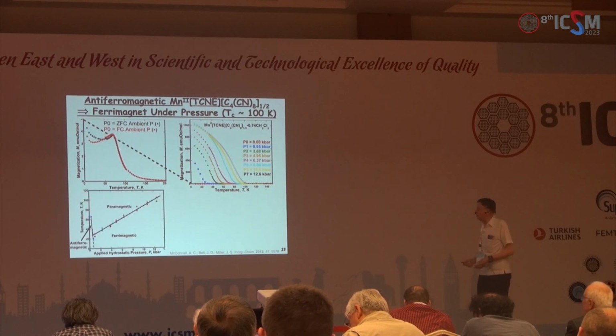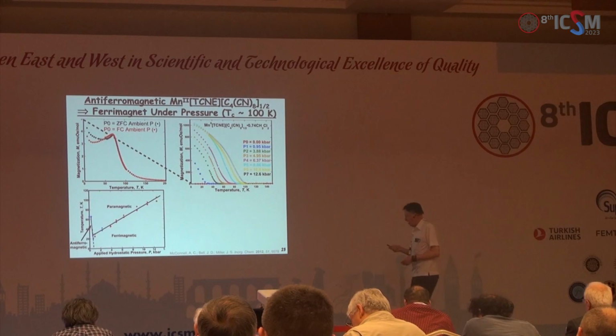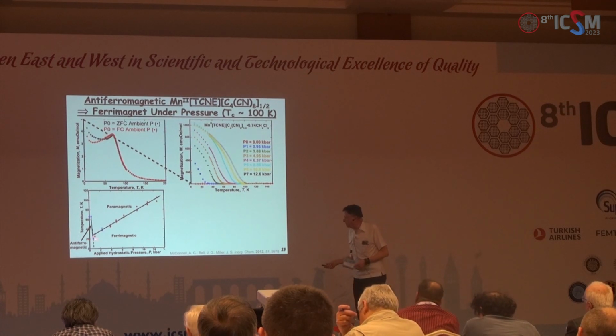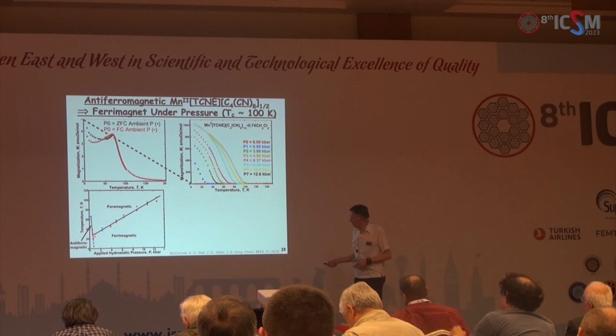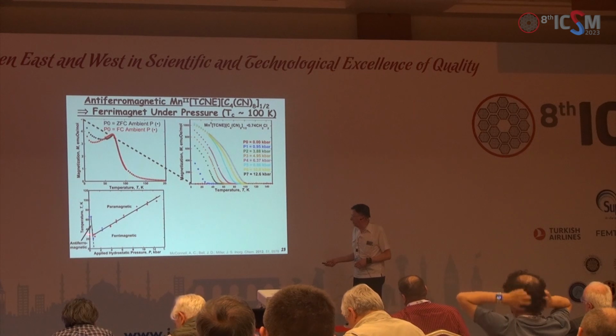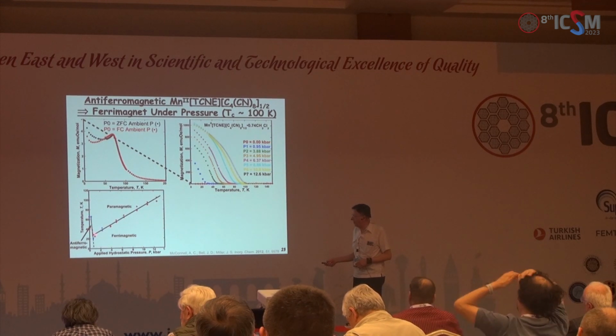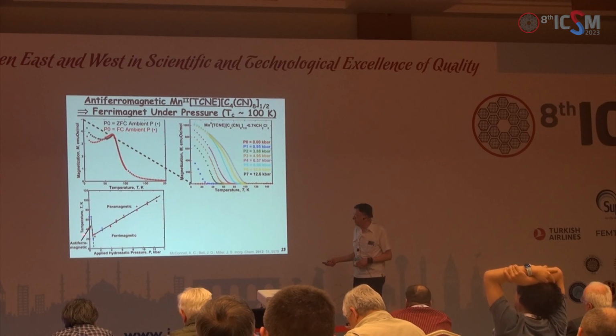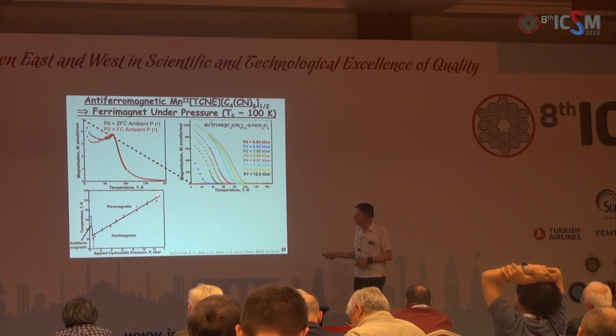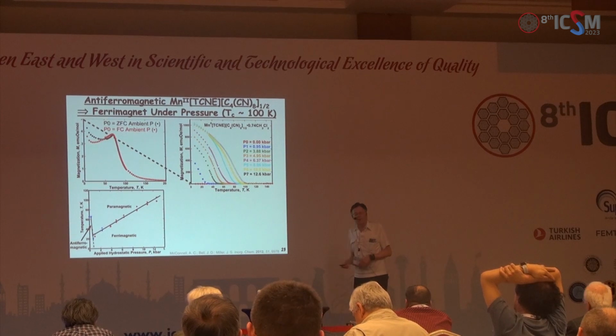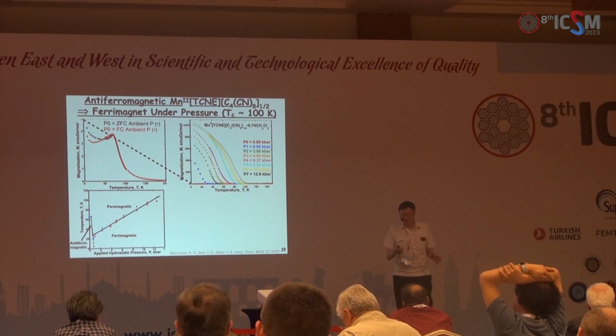If we look at the phase diagram, up to basically about 1.5 kilobars, it's antiferromagnetic, and then it kicks in to be a ferrimagnet whose TC increases linearly with pressure, reversibly—it goes right back to 0 if you reduce the pressure of the material.